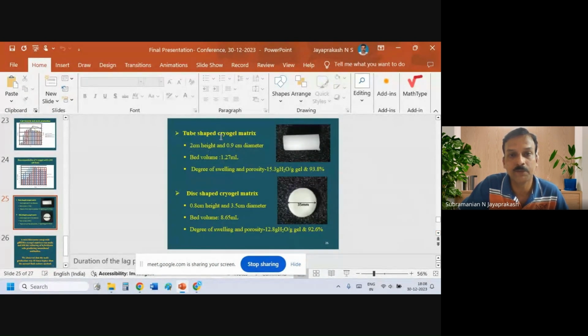And we prepared a tube-shaped cryogel matrix with 2 centimeter height and 0.9 centimeter diameter with a bed volume of 1.27 ml. And we also made a disc-shaped cryogel matrix of 0.8 centimeter height and 3.5 centimeter diameter with a bed volume of 8.65 ml.